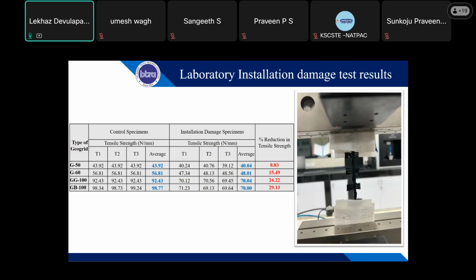This is a tensile strength instrument, usually a UTM, and we place the grid in between. We pull it and see the ultimate tensile strength of the specimen. You can see, before the testing, the control specimen tensile strength is nearly 43 for the G50 and 56 for the other. It was a manufactured product. For G100, the glass grid was nearly 100.